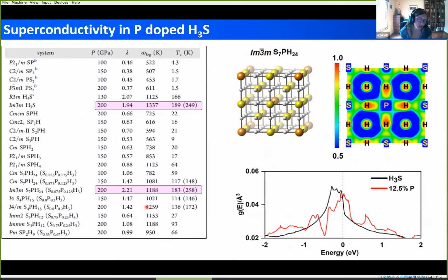We then took a look at filtering out the ones that potentially had a high density of states at the Fermi level from those that did not, and also took into account other considerations such as symmetry. We really can't do EPC calculations on very low symmetry structures when deciding which ones to consider for the superconducting properties.